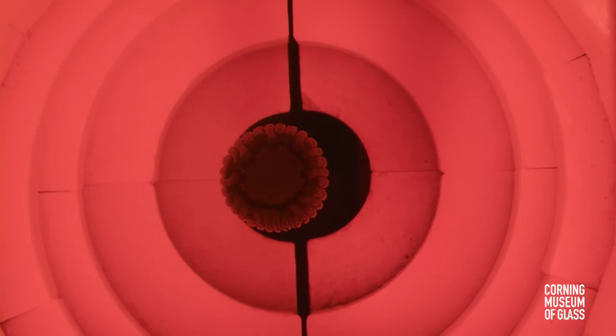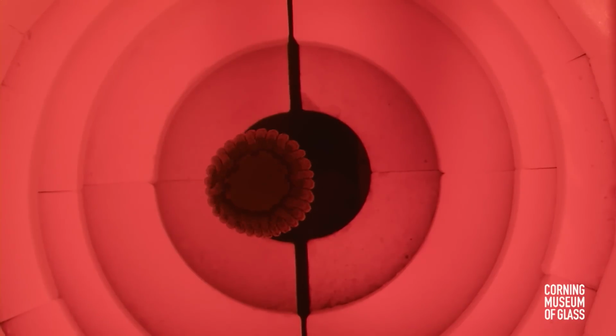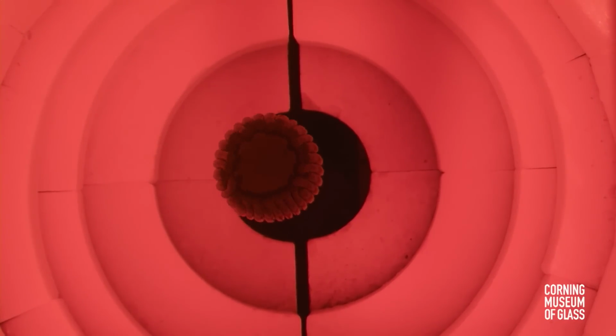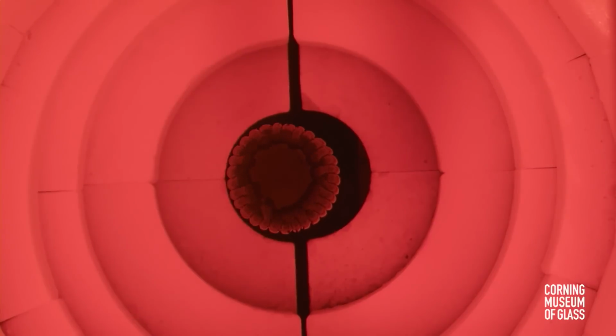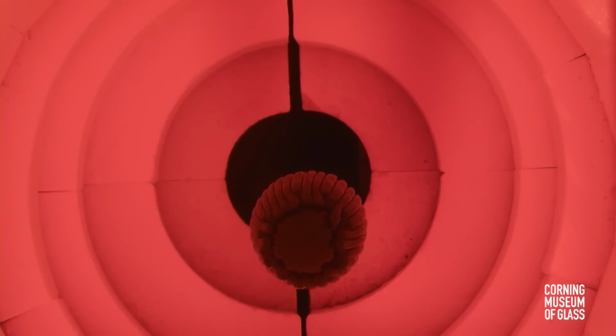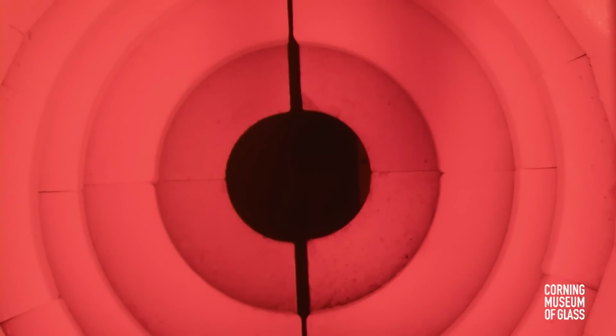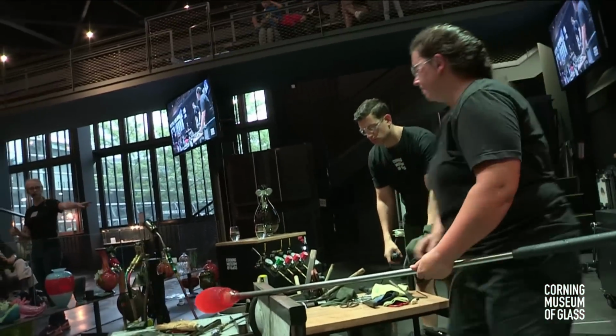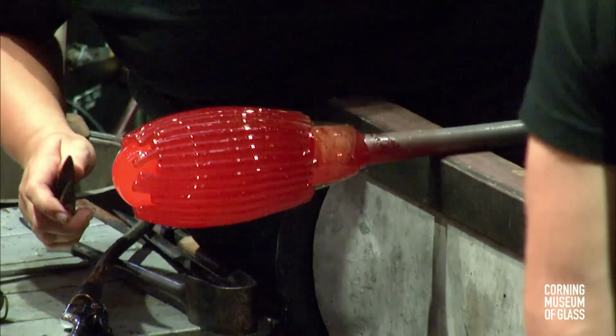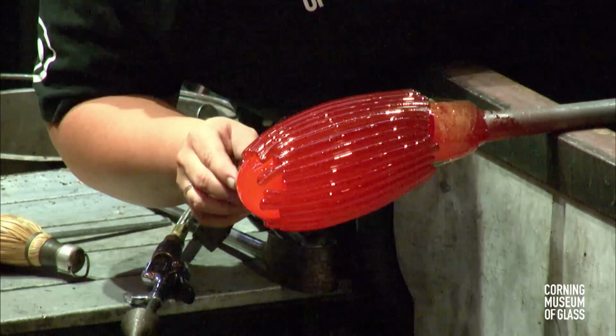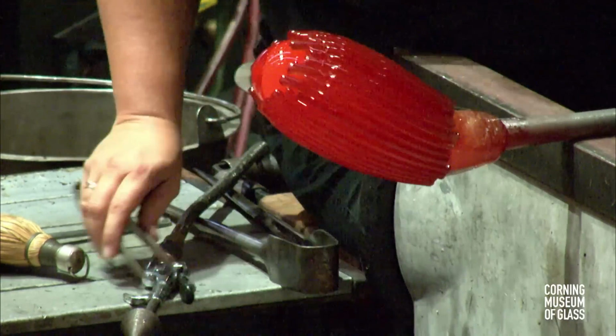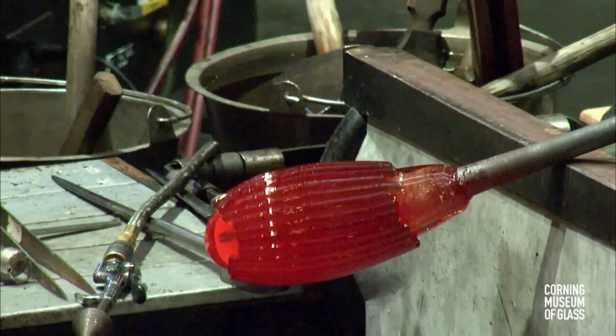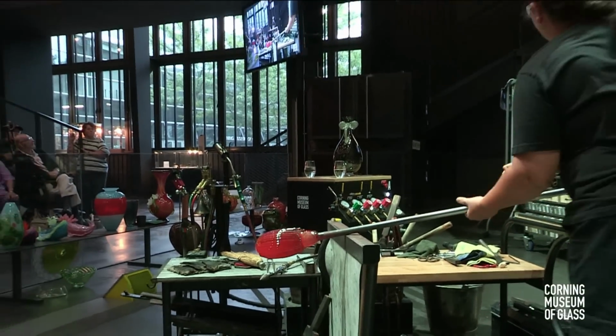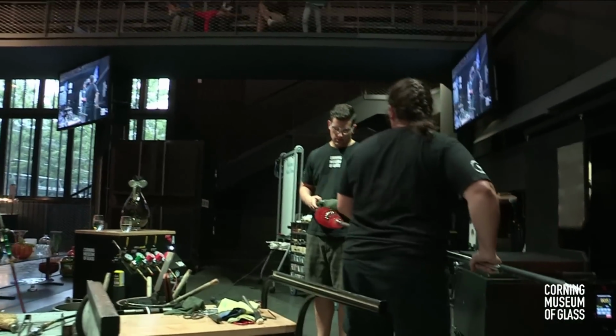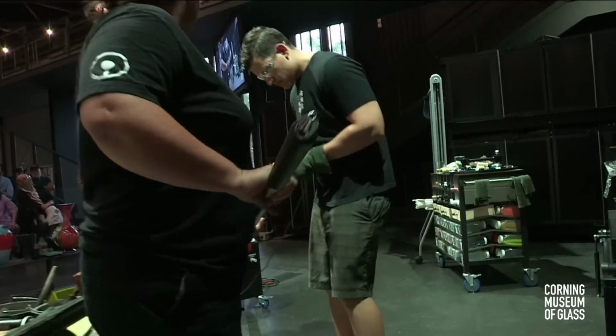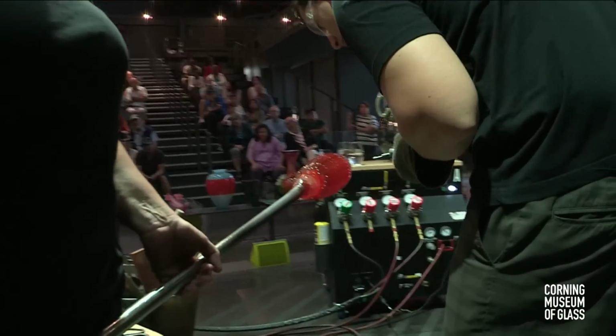Some people do that on purpose, like I mentioned, and we use that in a pattern called reticello, which we do not have up on the stage. So reticello is a bunch of canes in a cup, and they twist those canes or the lines in one direction. They put that cup in a special oven. That cup is held at around 1,000 degrees Fahrenheit until the glass blower is done with a second bubble of canes twisted in the opposite direction. They then take that second bubble of cane and twisted and plunge it down into the cup that they've held in the oven. When they do that, they trap little tiny air bubbles in between the valleys of the cane.